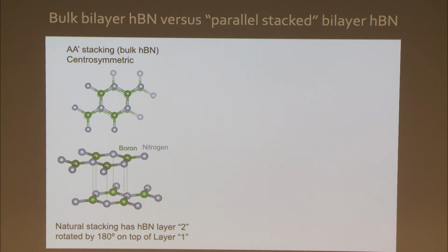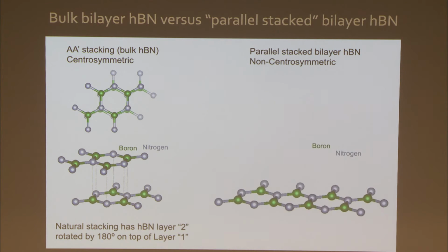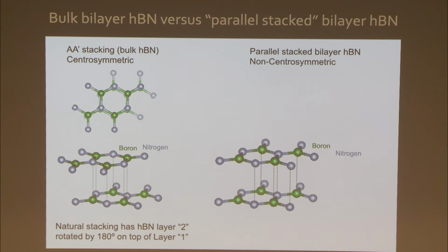Now, let me do the following trick. Since I can take a monolayer, break it into 2 pieces, and stack them at any angle that I want, okay? I'm going to actually stack them at 0 angle rather than 180 degrees. So I take a monolayer of hexagonal boron nitride. Then I put here lines to guide your eyes, and then I'm going to break it. I'm going to stack it parallel to itself, okay? Without rotating it 180 degrees like nature likes to do. I just do it at 0 degrees.